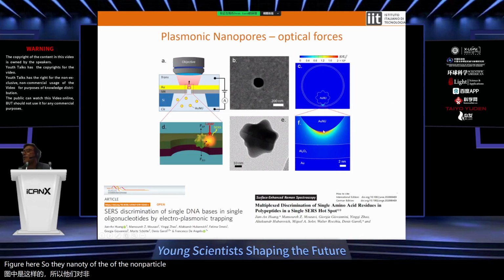nanoparticle goes in close proximity with the wall of the nanopore and generates this huge field confinement that can be called a nanocavity, and the volume of this cavity is comparable with the size of a nucleotide or an amino acid, because it's close to 1 nanometer cubed. Consequently, if you decorate this nanoparticle with your molecule, you can perform enhanced spectroscopy inside this cavity. And this is actually what we did.